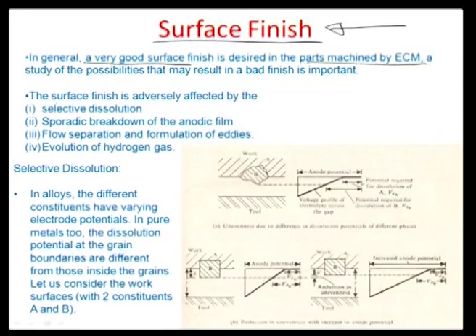So, for two reasons. One, the surface finish is adversely affected by these three or four processes associated with an ECM. One is the process of selective dissolution, another is the sporadic breakdown of anodic film. Of course, flow separation and formation of eddies, particularly related to local precipitation of the material coming out, etcetera, and evolution of the hydrogen gas. Okay. So, let us look at these different cases one by one as to how the surface finish is changed